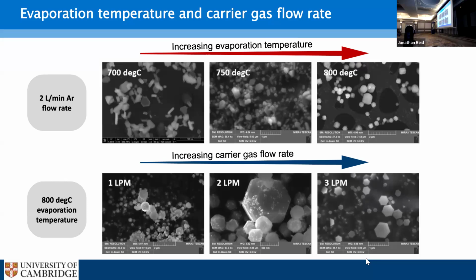That was my follow-up question. I was just curious whether, because you increase the gas flow rate, various things change, concentration goes down. But you said something about the temperature history changes as well, and also the residence time changes. So I was just wondering. It's really interesting work. Yeah, that's something that we want to look at more, because as you increase the carrier gas flow rate, they experience a much sharper temperature drop, and so they experience much more extreme conditions of supersaturation.